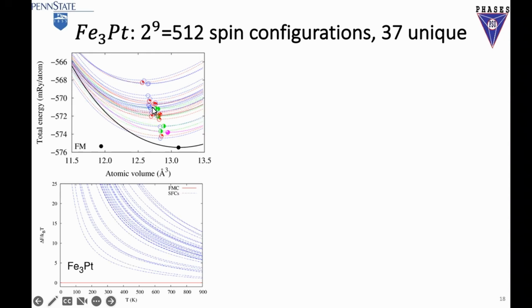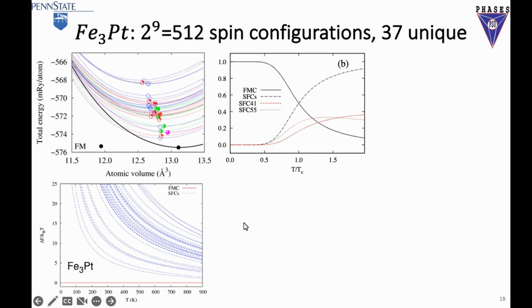Nothing should happen. However, the difference between the blue ones, the metastable, and the stable one is decreasing as temperature goes up. That means the probability of a metastable state increases when temperature goes up. They are not stable, but they have statistical probability. So we can calculate the probability of the different configurations, microstates. The black line here is the ground state at this very low temperature, 100%. It's all ground state. However, when temperature increases, you can see that the non-ground states' population starts to increase statistically.